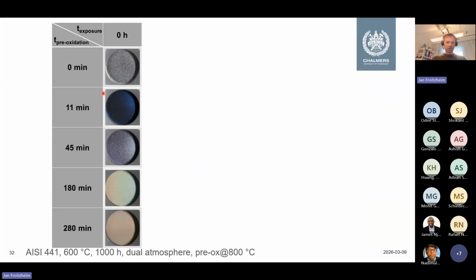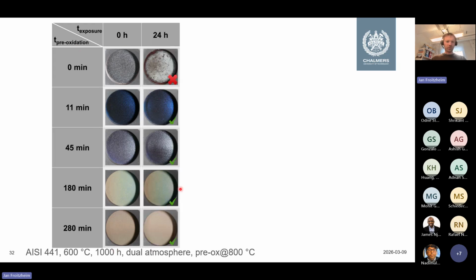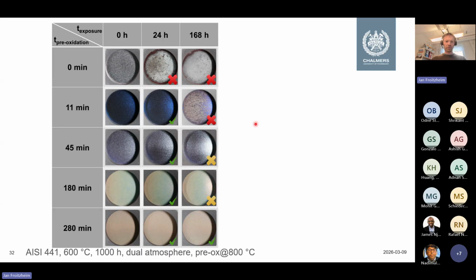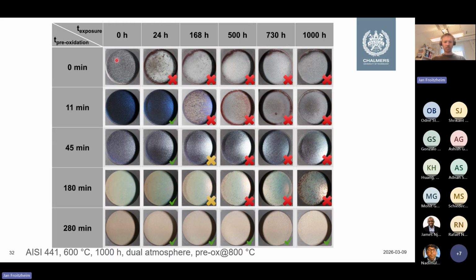So we looked at pre-oxidation as a parameter. These are samples pre-oxidized for different times. This is before exposure, nothing happened so far. After 24 hours, you see the non-pre-oxidized samples already dead, while the other samples survive. Then if you go longer, after a week, the shortest pre-oxidations are dead while the long ones look okay, and that basically continues. So you get some kind of line, I don't know if it's straight, but there's some kind of trend.